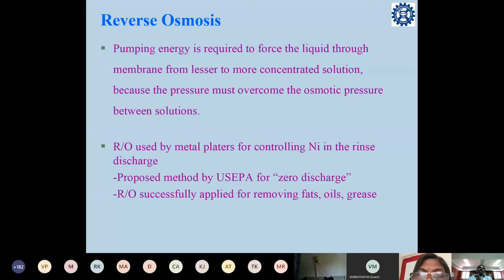So here large pumping energy is required to force the liquid through the membrane from lesser to more concentrated solution, because the pressure must overcome the osmotic pressure between the solutions. The natural osmotic process that occurs in the solutions creates some pressure. So to overcome the pressure, we have to apply pressure on the opposite side to make this process get reversed. Okay. Then RO is used by metal platers for controlling nickel in the rinse discharge. RO is also successfully applied for removing fats, oils, and grease. So that is the advantage of using this RO process.